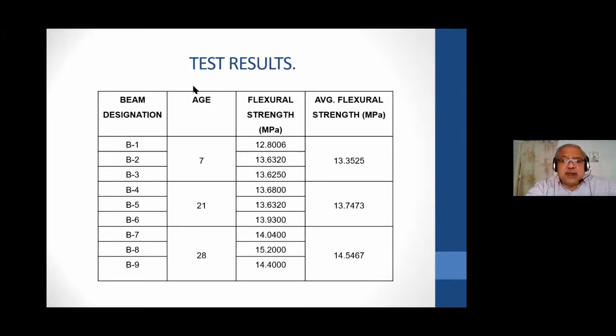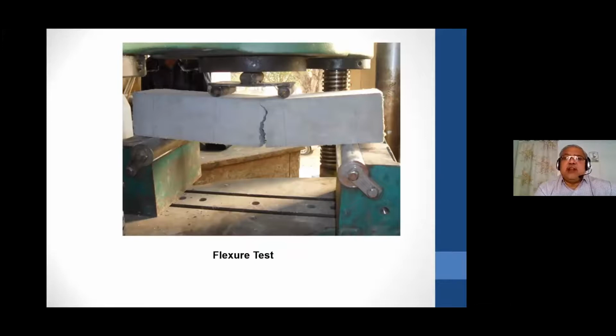Not only this, as the age goes up, the average flexural strength also goes up. That is one point. Of course, we could not wait for a long time, but I am very sure that at the end of 58 days, this could have been around 16 or 16.5 MPa. That was the expectation. This is how the flexural test went.